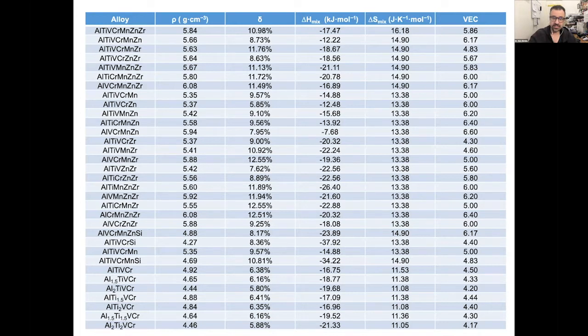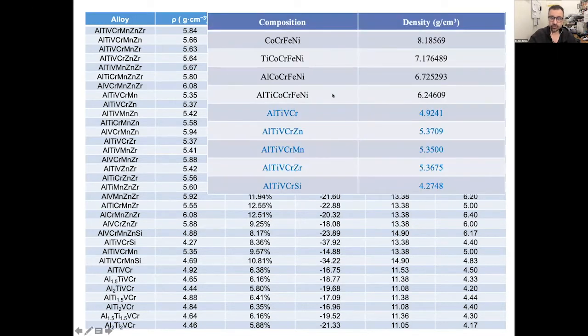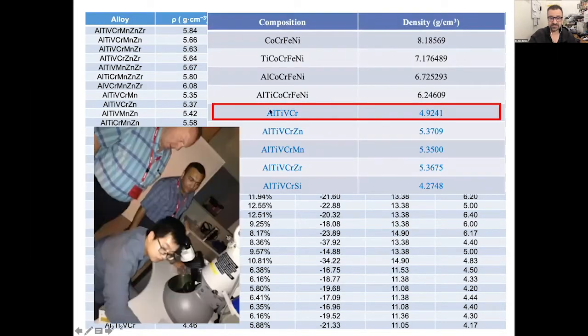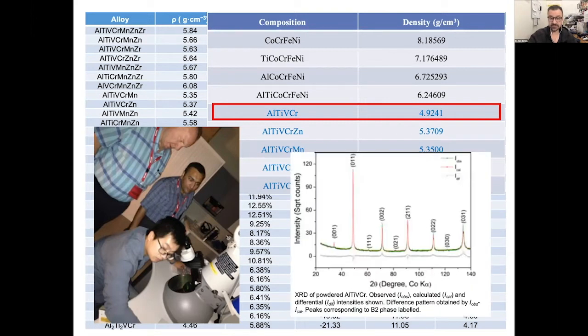And he shortlisted it down to a small number of alloys and then a final system, which was a 4-component system that had a high entropy of mixing, should be single phase with a very, very low density, or at least very low compared to steel. So here's Yao here on the TEM where he did most of his best work. And it turns out that when you make this alloy, and you can make it by many means, we typically made it by arc melting, it actually was a single phase alloy.